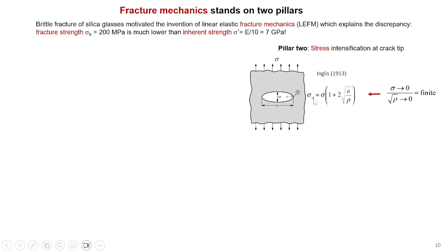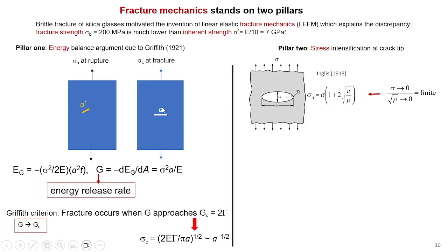So that's a good starting point, except if you look at it, when this hole or this flaw is infinitely sharp, the stress will be infinitely high at the tip, which is annoying. And Griffith, for reasons I need to wake him up from the grave to ask, gee, why does that bother him? It really bothers him. So he decided to work on looking at the condition for a flaw that you can pretend by digging a hole, and under what condition this flaw will lead to crack growth.